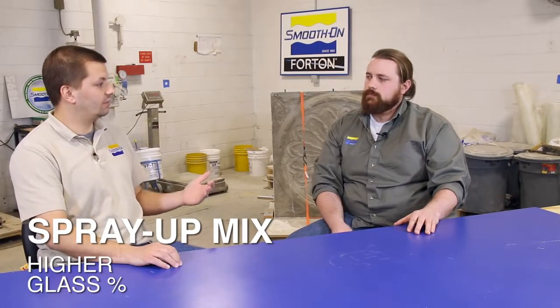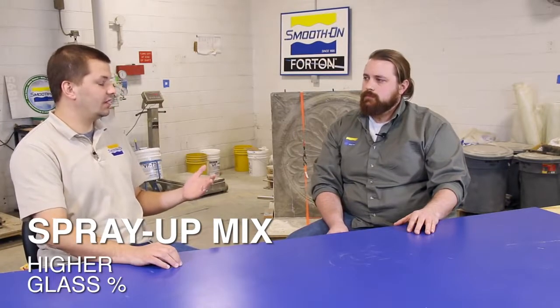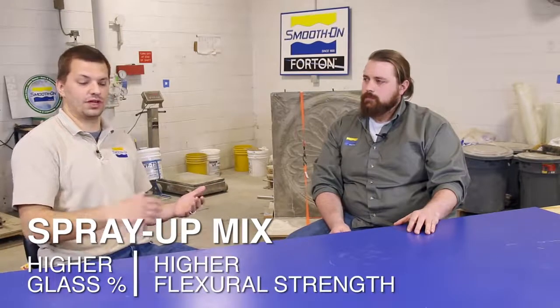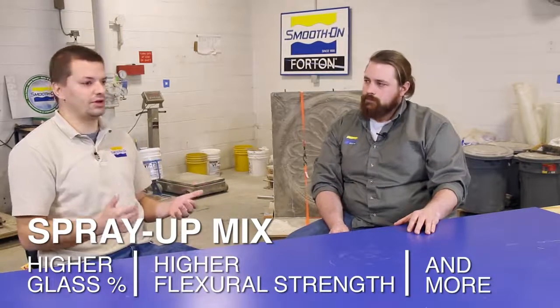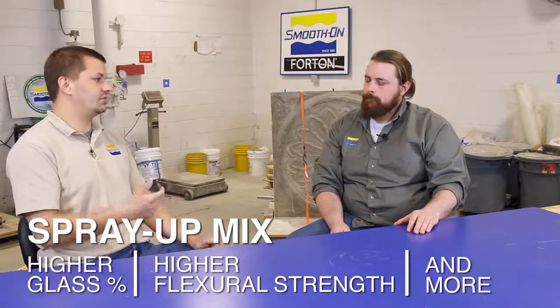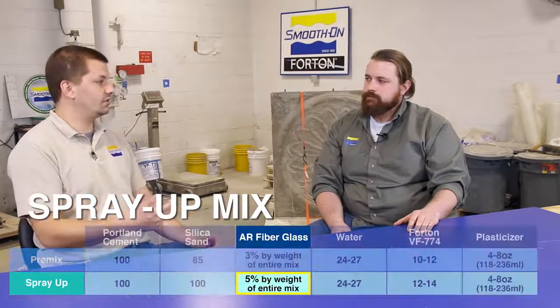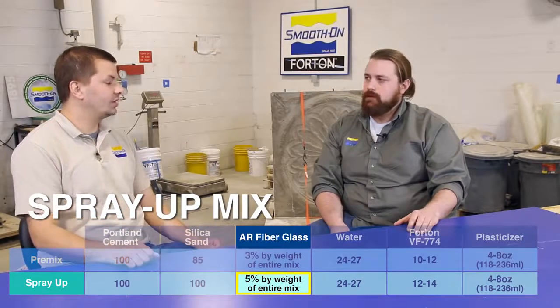And if you look on our technical bulletin, the spray up mix design ultimately has higher flexural strengths and a number of other higher physical properties. That's because with that system, you can get up to 5% glass loading in the entire mix. Yeah, very difficult to pre-mix that much glass and get good placement of it ultimately when you're doing a pre-mix application. Right? Yep, but still a great mix design nonetheless.